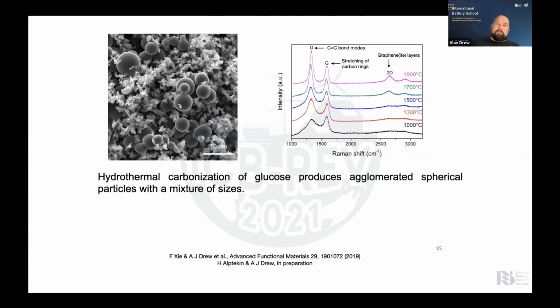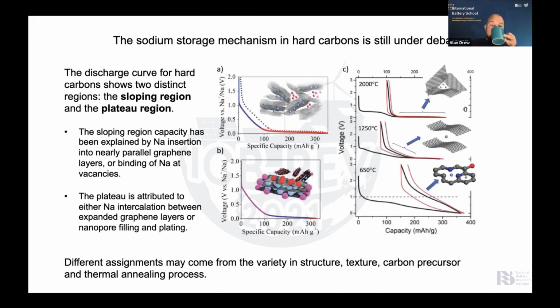Okay, here is an example of hydrothermal carbonization. It's a bit of a mixture, as you can see, but you can see fluorescent-like nanodots in one case, or in this case, the microdots. And in other cases, you can see a very porous structure. As you increase the annealing temperature, the pyrolysis temperature, from 1,000 degrees C to 1,900 degrees C, you can see a graphite peak appearing on the Raman spectroscopy. So as you increase the temperature, you increase the order, okay?